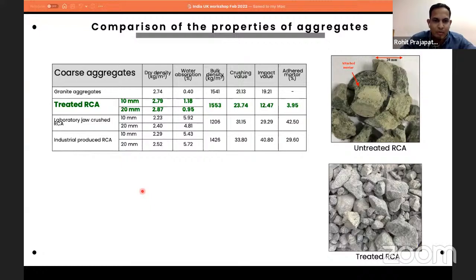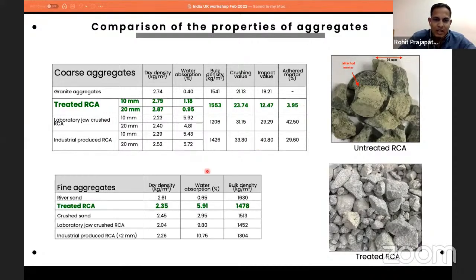Just to show you some properties, we have compared the aggregates with pristine granite aggregates, laboratory jaw crushed aggregate, and we also got aggregates from the industry. You can see that the water absorption is comparable, and we were able to remove almost all the adhered mortar, up to 96%. Similarly, for fine aggregates, we were able to improve the water absorption to almost 6%, which is 40% less than the untreated recycled aggregates.